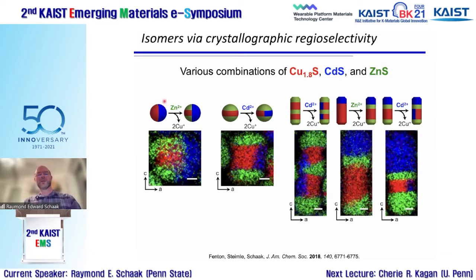So for example, we know that if we have a sphere of copper sulfide and we do a partial cadmium exchange, the cadmium comes in from a side. We can make a particle that has one half cadmium sulfide, one half copper sulfide. We'll take the copper sulfide side. We know if we do a zinc exchange on copper sulfide, it comes in this way. So we can start with this half-half copper sulfide cadmium sulfide particle and then come in and do an additional exchange reaction, that sandwich reaction, and we can basically make half a sandwich on one side with a hemisphere of cadmium sulfide on the other for a particle that looks like this.